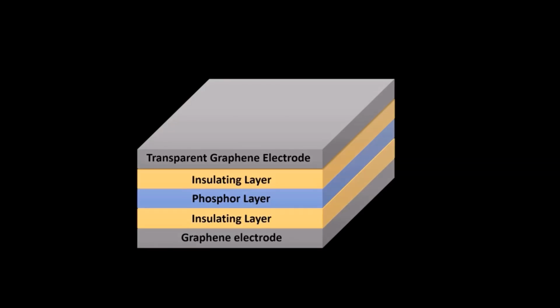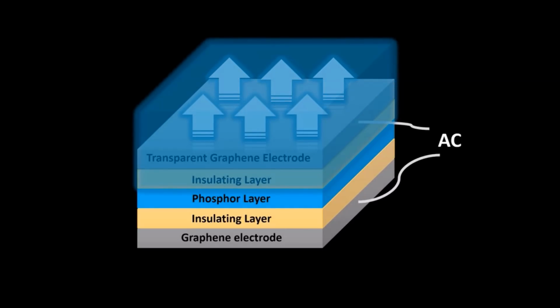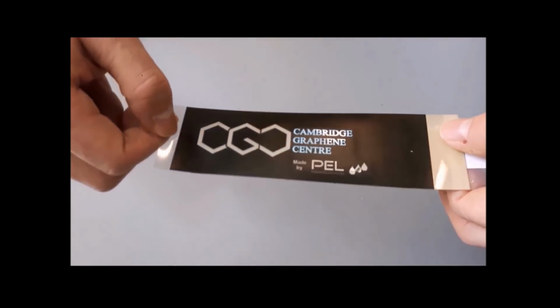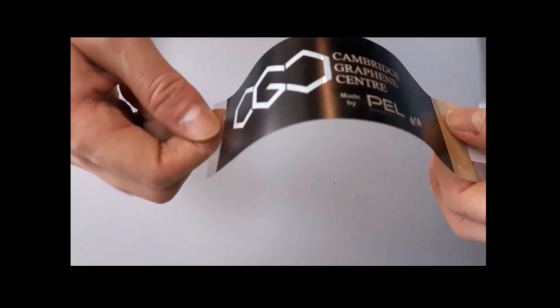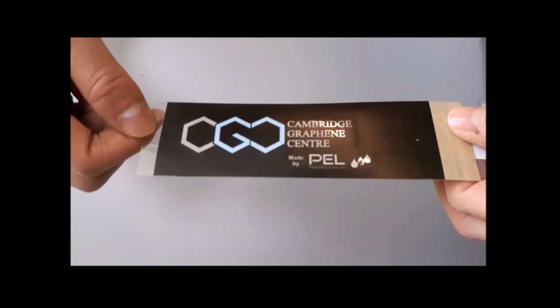However, you can go to something more complex, where here we have a multi-layered structure. We're looking at a graphene back electrode, which is thick and black, but on top we have a transparent graphene electrode. So this is a printed layer, which is a different kind of ink, but we're printing a few nanometer film thickness. And in between that, we've sandwiched a phosphorescent material. So when you apply a voltage between these two electrodes, you can make the phosphor light up. So we can make some flexible lighting modules. Here we can see a schematic, and here's the final device where you can see the light shining through the transparent graphene top layer. So that's just a couple of simple applications that we can do using printed graphene inks.